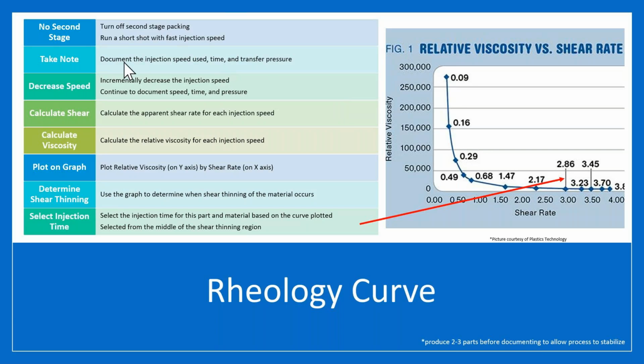We're going to make sure that we're documenting the speed, the time, and the transfer pressure at each iteration. We're going to conduct a series of 2 to 3 injections at each velocity set point and document the speed, the time, and the pressure. From there, we can calculate an apparent shear rate, which is going to be 1 over the fill time. And then we can calculate an apparent viscosity, which is going to be the injection pressure times the fill time.